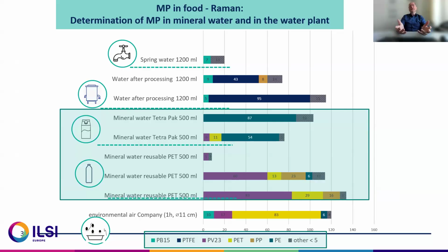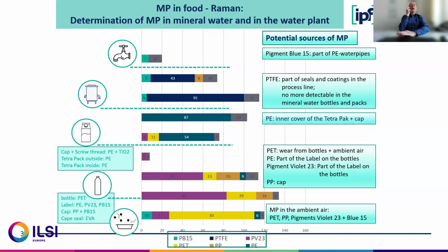Sometimes the bottle is clear, and sometimes you have mostly pigments in the bottle. In comparison to the Tetra Pak, here we have no pigments or very low, and instead of that, the polyethylene particles. However, the spring water is clean, so there's no entrance from the spring water. The processing water is also clean. What we found is only PTFE. That means this is a part of the seals, and we used it for the sampling site, and maybe it was a long time not open, so that means here's also no entrance. So that means that the polyethylene comes from the inner cover of the Tetra Pak, and the PET is from the bottles.